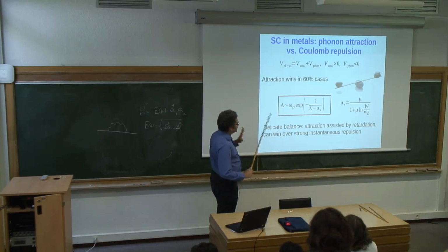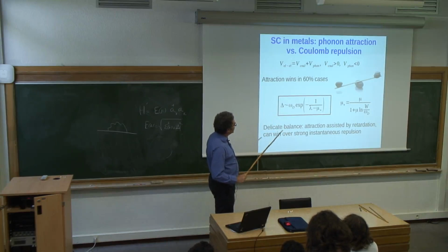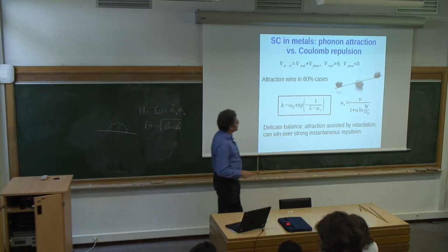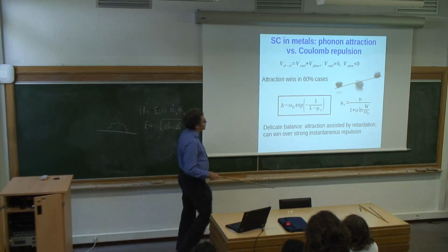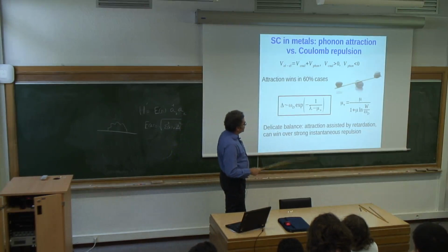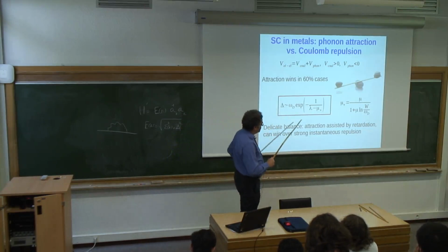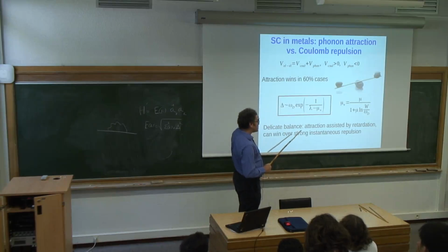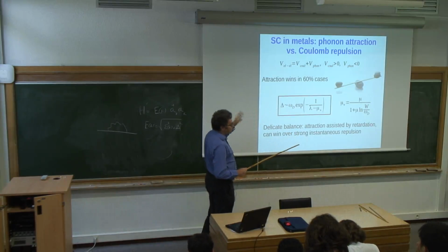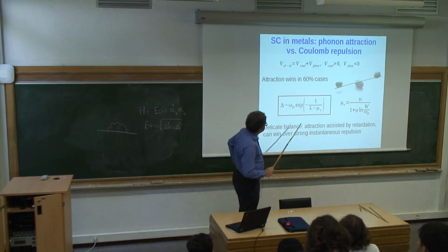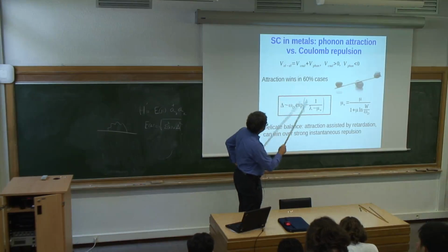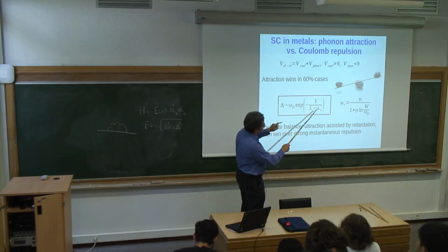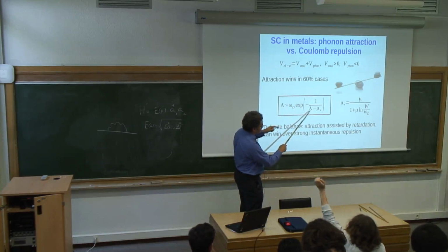And in fact, I think out of all metals known, conductors known, there are about 60% which are superconducting at some temperature, and others aren't. However, the way you see it in the formalism is that if you put both Coulomb interaction and phonon interaction in that approach I discussed, and you have to do it a bit more carefully than what we did, you find that both coupling strengths appear in this BCS formula, and the phonon coupling appears the way we discussed, but then the Coulomb interaction gives a negative contribution to this coupling, so it suppresses lambda.